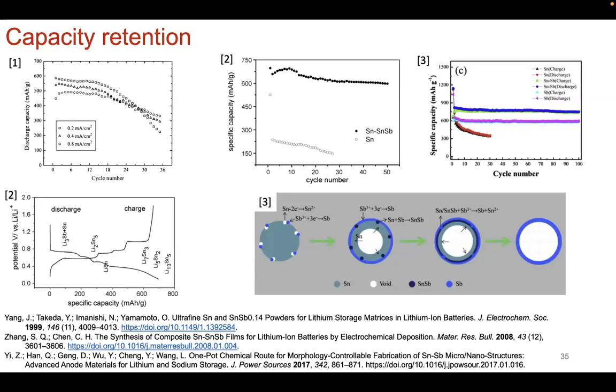In terms of capacity retention, all these examples basically show that when you have these two-phase mixtures, you have increased capacity retention, you have increased initial capacity, and then you can get really complex with all these designs. You can also introduce core-shell type structures. You can also introduce nanostructures with voids, so that any growth of the lithiated phase will grow into these voids and be encapsulated in these voids, so as to not pulverize and rupture your electrode, which is also the strategy for all the other anodes that we've already talked about. Okay.